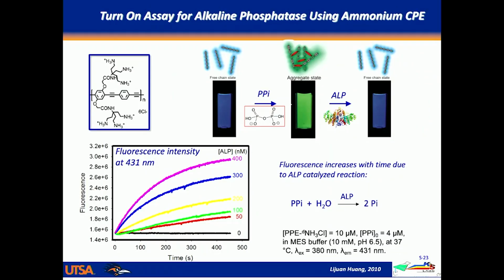And so that's what I'm showing you here. So now the system is simpler. We don't have copper. We don't need the divalent metal ion present. We just basically start out with the fluorescent polymer. We add the phosphate to it. It aggregates. And then we add the enzyme. And the enzyme catalyzes the hydrolysis reaction that's shown here. And during the hydrolysis reaction, the polymer is deaggregated and it becomes blue fluorescent again.